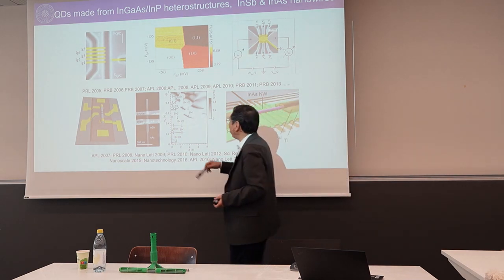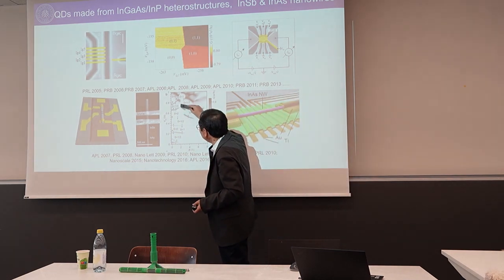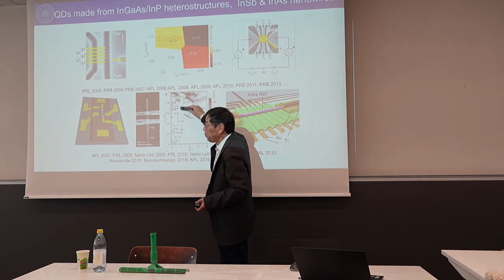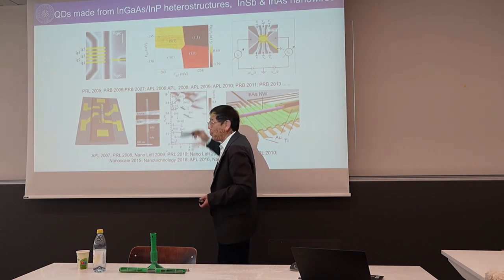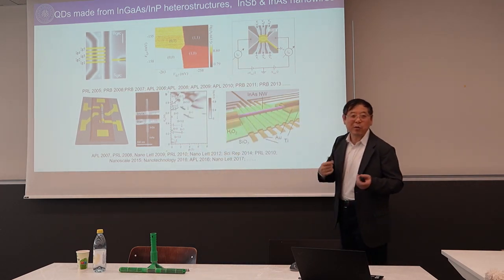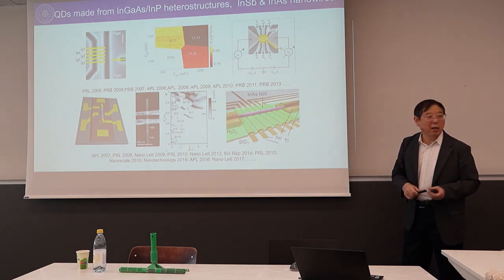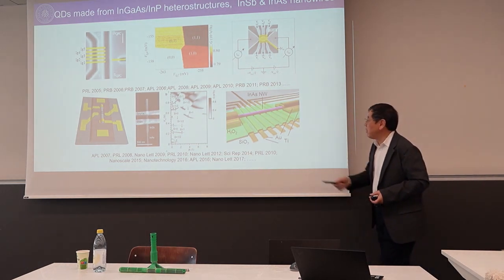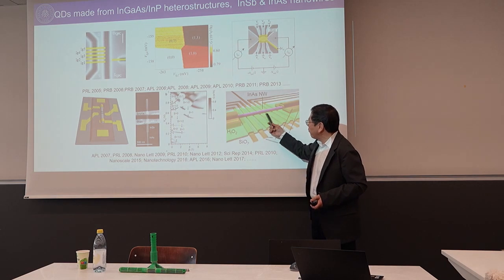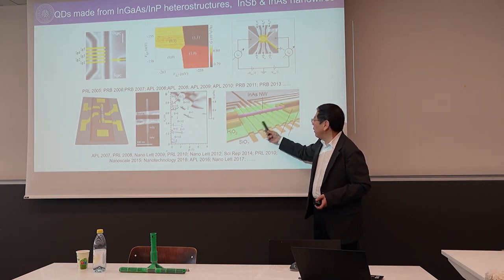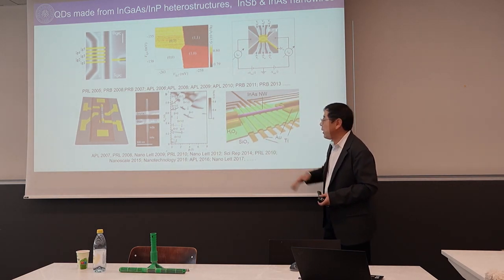So we also see some here. The essential thing is, there is a Kondo correlation, but there is suppressed conductance. So I will go there slightly. Maybe that's a long time of work we published. And this is indium arsenide nanowires we grew in China, and this work was done at Peking University.